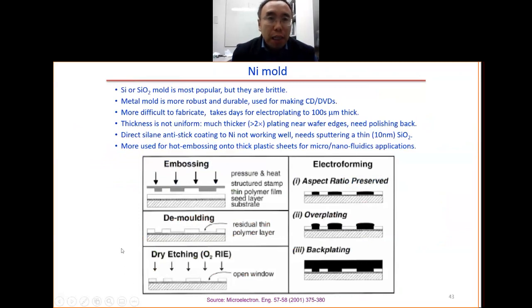So now let's look at the nickel mold. We know that the silicon mold, the silicon oxide mold, the problem is they are very brittle. It's fragile. It breaks easily. So the metal mold is not brittle. It can be used many times. Actually, CDs, DVDs, and Blu-rays are made using a metal mold by the injection molding process. But the metal mold is more difficult to fabricate, costs at least $10,000, and takes some days, 1 day or maybe even longer, to plate a very thick layer of the metal.